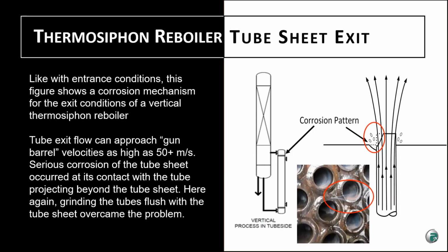This particular example showed the corrosion that occurred at the exit of a thermosiphon reboiler. The tube and the tube sheet showed quite severe corrosion pattern because of the high exit velocity achieved inside a thermosiphon reboiler. The only way that we could correct the problem was to grind the tubes so that they were flush to the tube sheet exit, and that definitely improved and reduced the corrosion potential inside this system.